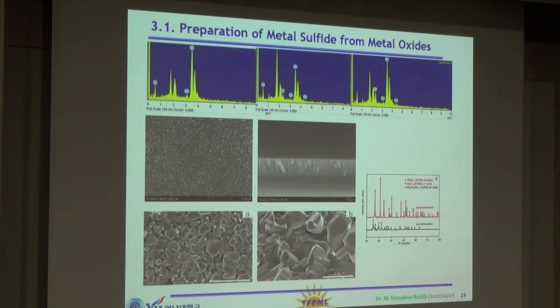After the preparation of the layers, we measured the EDS. From the EDS, we confirmed the sulfur incorporation in the layers, but there is still some portion of oxygen in the case of a smaller amount of sulfur. Whenever we added more sulfur, we almost eliminated the oxygen, and we were able to produce tin disulfide instead of monosulfide.